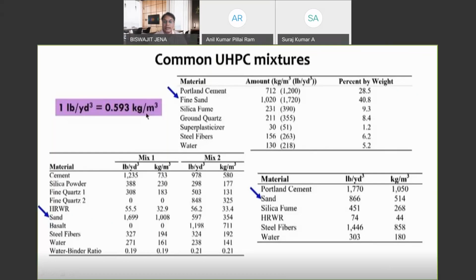The second reason is that I need a lot of fine powders. Cement being a fine powder, the properties of which you know really well, you can control. And that is why, for these two reasons, we generally use a high amount of cement. But in that case, the downside is high shrinkage. So that is why this has to be really well controlled in terms of curing and in terms of using materials like internal curing admixtures or super absorbent polymer, something like that.